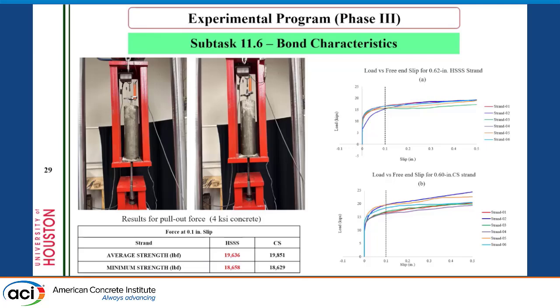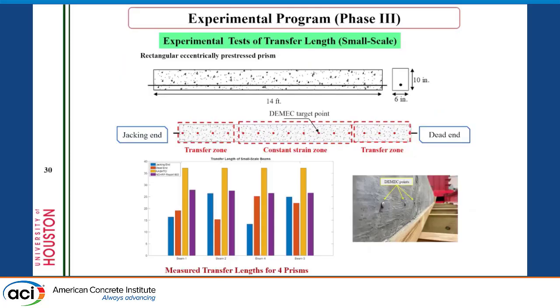This is just an example for the 4 ksi concrete, where we got the same pull-out force test. We confirmed that, even in the FEM, when we used the same friction coefficients, we got the same transfer and development length, because the bond has to do with the transfer and development. The next step, after we defined the bond characteristics between the concrete and the stainless steel strand, was some small-scale and large-scale testing to measure the transfer length.